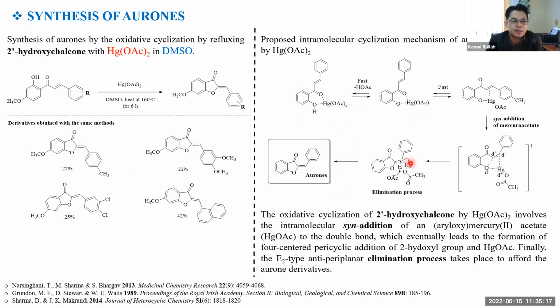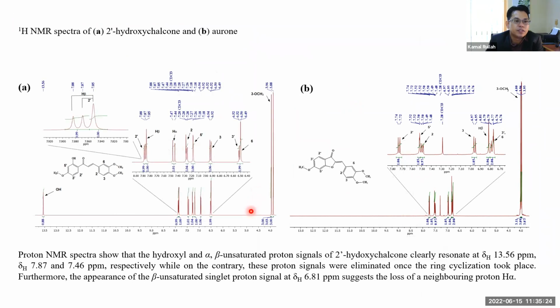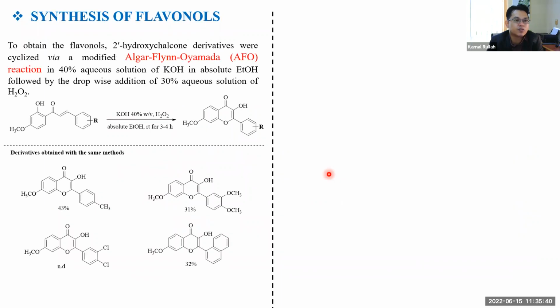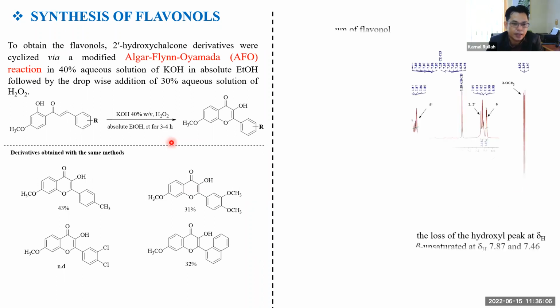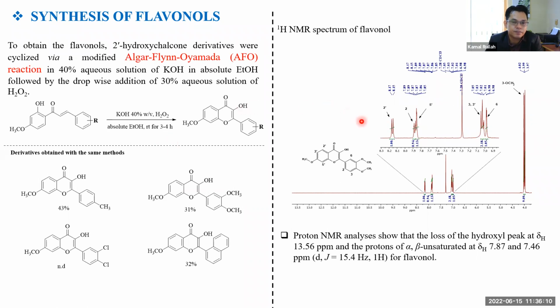I'm not going into the detail of the intramolecular cyclization mechanism here. And this is the proof by NMR that I have successfully synthesized the aurone from the chalcone. Next, we have also synthesized the flavonol. Flavonols were obtained by the modified AFO, Algar-Flynn-Oyamada reaction of the chalcone in 40% aqueous solution of potassium hydroxide in absolute ethanol, followed by dropwise addition of 30% aqueous solution of hydrogen peroxide. The NMR results show the success of the synthesis of flavonol.